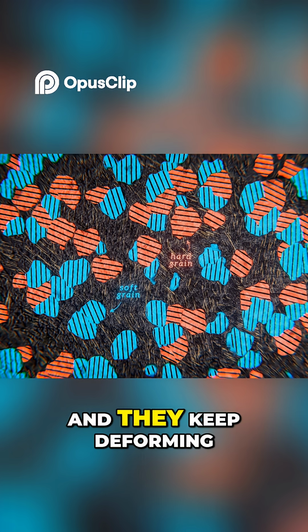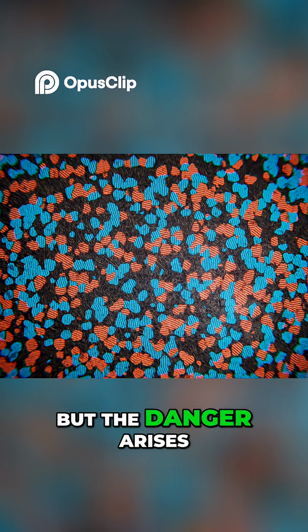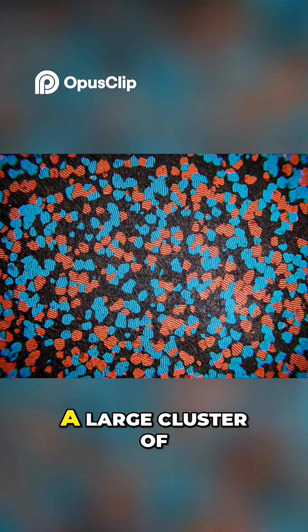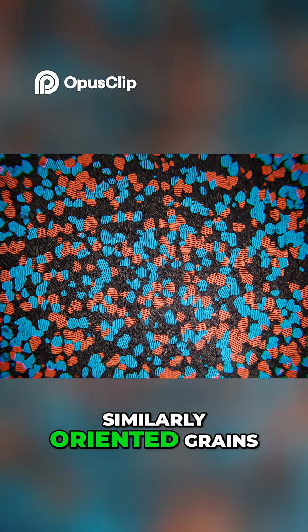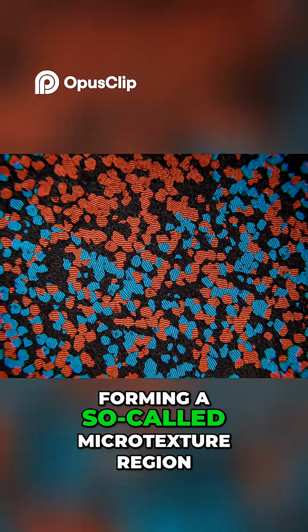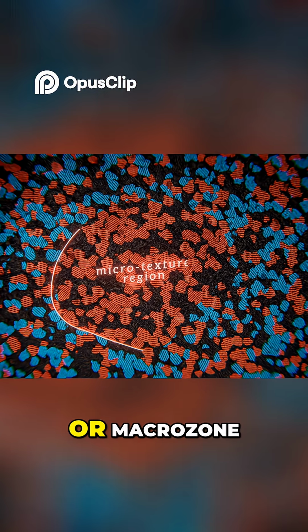keep deforming over time when the load is held, causing the load to redistribute and gradually shift onto the harder regions. But the danger arises when the material contains a large cluster of similarly oriented grains, forming a so-called microtexture region or macro zone.